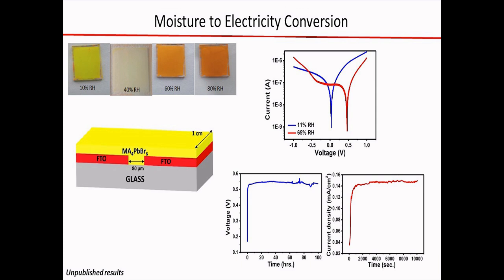So we measured the open circuit voltage. We saw that at 11% humidity, there is no voltage generated, but as soon as we switched it to 65% RH, there is actually a certain voltage generated from this device. This is measured only in the dark. So the open circuit potential that we are seeing is coming from the material itself.